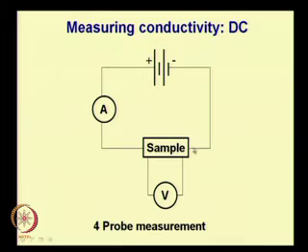Okay, the circuit outside the sample only has wires which can only conduct electrons. So the wires outside will not conduct the ions anywhere, in the more general sense that I am talking about. Therefore the ions are now confined to move within the sample. Therefore if you simply put a DC power supply and attach it to the sample, you can only send current